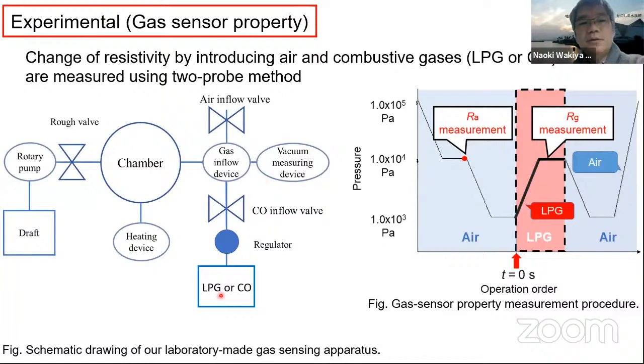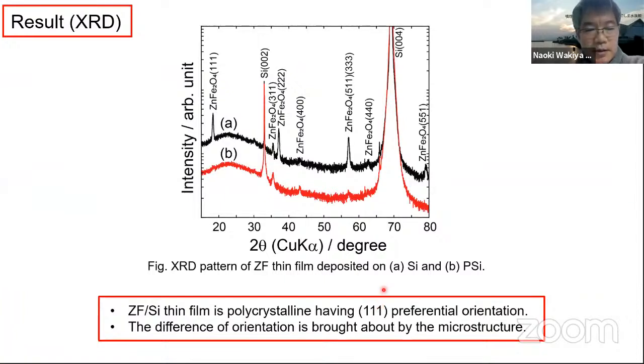In this case, we measure the sensor response for LPG and CO gas. And this is the gas sensor property measurement procedure. First it's air, then LPG or CO gas is introduced, then evacuate and air is introduced again. So this is an XRD pattern of zinc ferrite thin film deposited on A, silicon, and B, the porous silicon. So the zinc ferrite thin film is polycrystalline, having 1-1-1 preferential orientation on the silicon substrate.